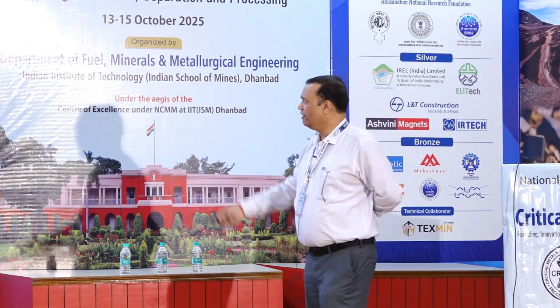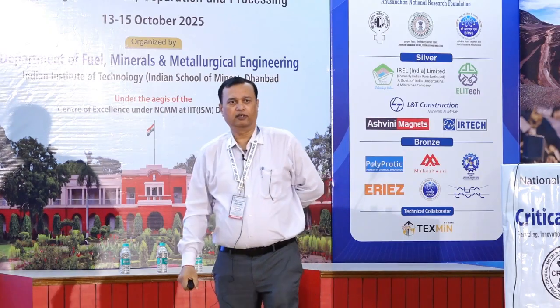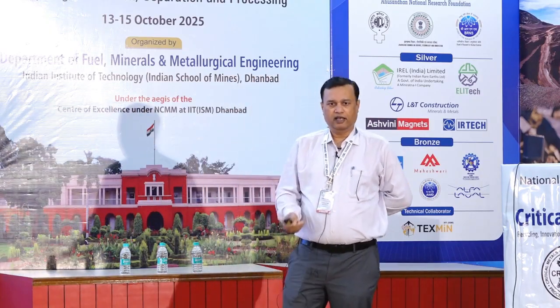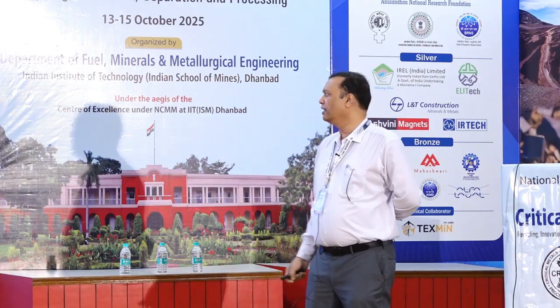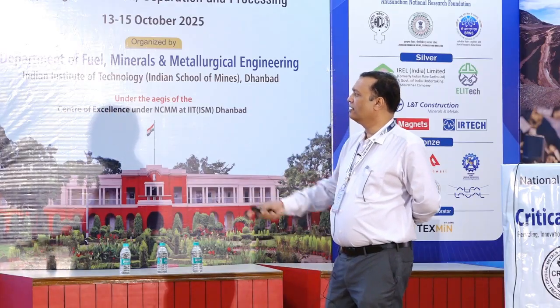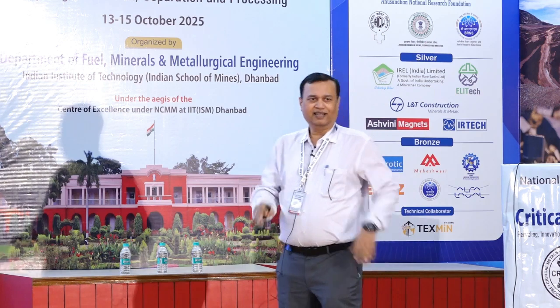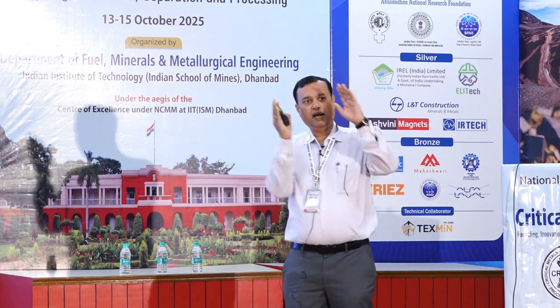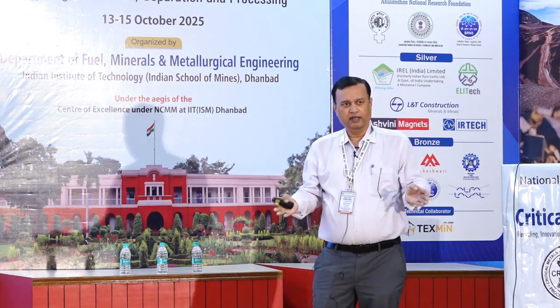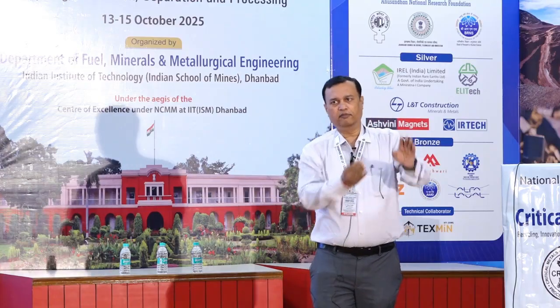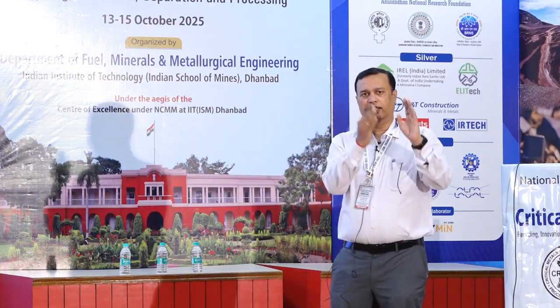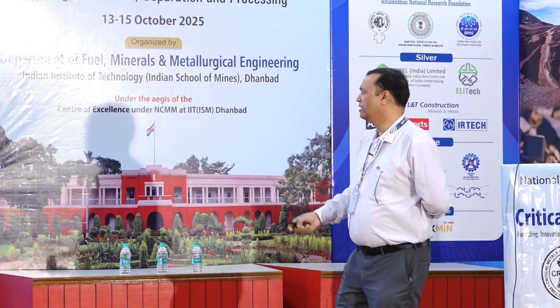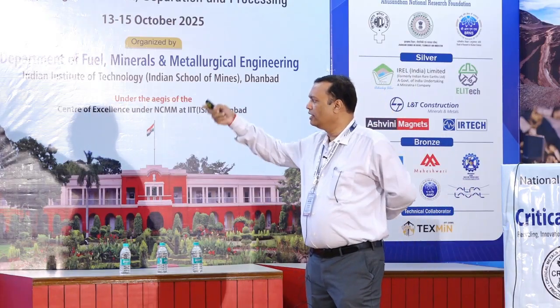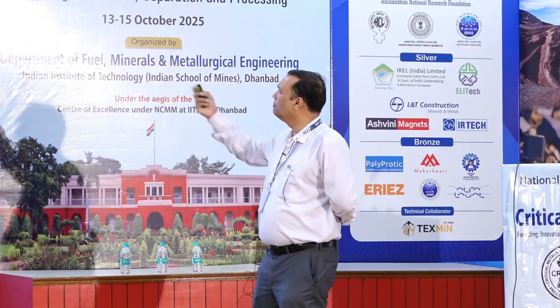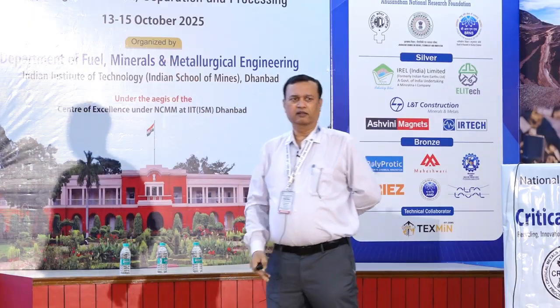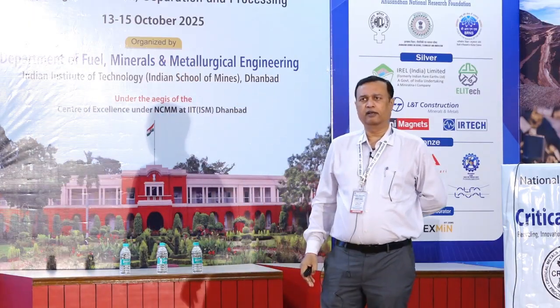So finally we will add Dy also, because, as I told you, Dy couples antiferromagnetically, and that gives the major push to the coercivity, and from 13 kilo-oersted we directly jump to 30 kilo-oersted. That happens because Dy goes into the matrix of NdFeB instead of the grain boundary. First the grain is decoupled, then we put Dy in the matrix, in the grain itself, and that increases the coercivity drastically to 30. And with this we were able to develop 200 grade NdFeB magnet that is widely used in electric vehicles.